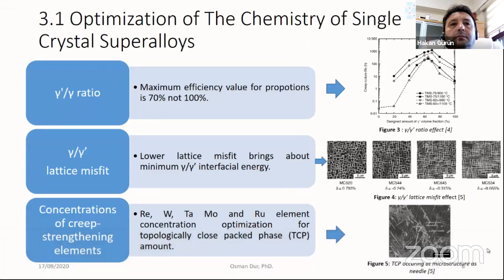For the optimization of the chemistry of single crystal superalloys, there are three different ways used by alloy designers. The gamma prime, gamma volume fraction should be designed very attentively because this ratio gives maximum efficiency at 70%, not 100. Gamma prime is used as a strengthening phase, however, it should be added sparingly. Lattice misfit is another concern for optimization of chemistry. Lastly, the creep strengthening elements should be added attentively because these elements can cause topologically close packed phase to occur. This phase can reduce creep life as a needle form inside the single crystal structures.